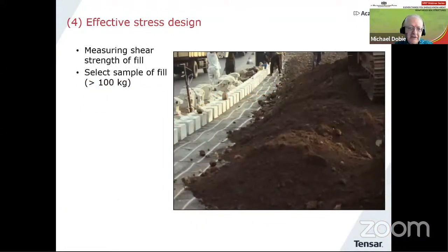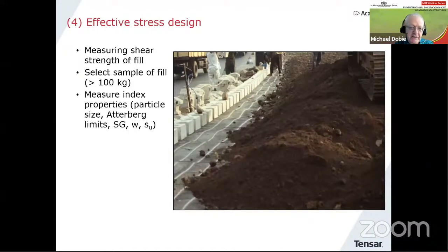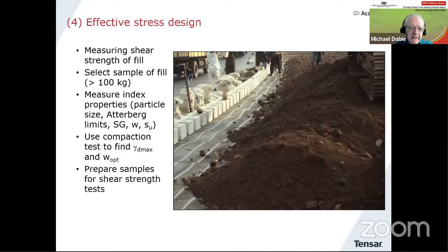So what do we do? Well, we go to site, we get a nice big sample of fill, and then we carry out all sorts of index property testing to find out what the soil consists of. We maybe classify it. And then we normally do a compaction test to find out information about the optimum water content and maximum dry density. And then, having done that, we can prepare samples to carry out shear strength tests.